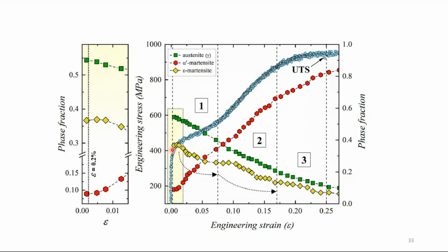When you reach this point, the yield strength, you are going to have, let's say, 60% of austenite at this dashed line that corresponds to the yield strength. Okay, and now we have epsilon martensite more than 35%, and we have less than 10% of alpha prime martensite. This is at the point when it reaches the yield strength. However, when you start applying the plastic deformation, you are going to see that the austenite is transforming, decreasing in amount during this process. Until the end, you get about 10% of austenite.